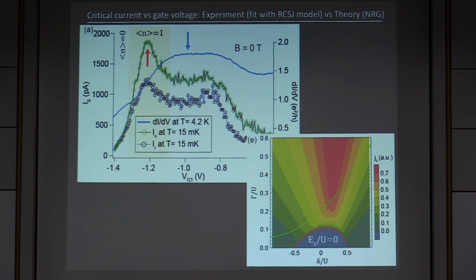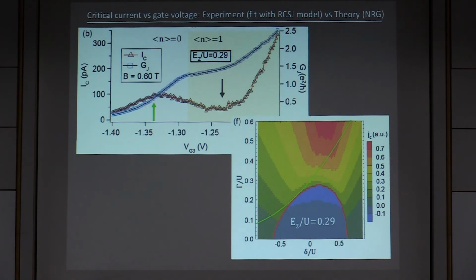So this is the phase diagram that you have already seen before at zero magnetic field, and this is how we scan through the phase diagram as we move the gate voltage. Because there is a variable gamma, as I said in the beginning, it's very important. In the superconducting regime, we see a peak in the supercurrent. This is the measure of supercurrent, switching current, and retrapping current. There's a peak in correspondence of this shoulder in the normal regime, which corresponds in the model to this peak over here.